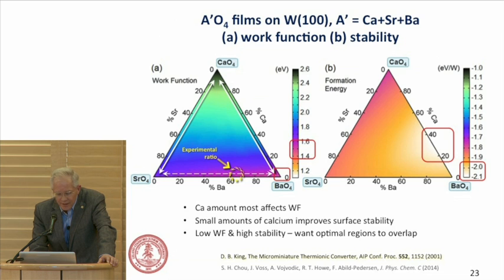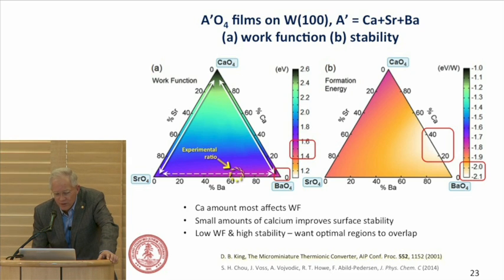And so, in fact, if you look at the pure films, it looks like you can benefit going to, and so I'm mapping pure barium oxide and a work function of around 1.5. And in fact, if you look at what calcium is doing, the addition of calcium is in fact driving the work function higher.